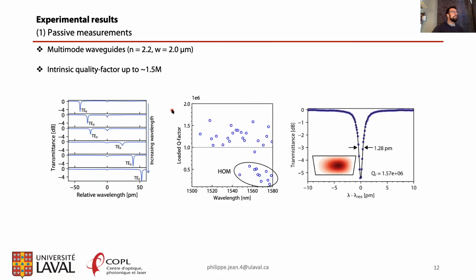Okay, next we move on to optical measurements. And here you can see the summary of the passive measurements. On the right, you can see a single resonance with a relatively high quality factor of 1.5 million. And you can see multiple quality factors that were measured for the fundamental quasi-TE mode that range between about 1 million and 1.5 million, which is pretty good for integrated chalcogenide photonics. Although it's important to mention that it's not really on par with what's being done in other platforms such as silicon nitride or tantalum pentoxide.